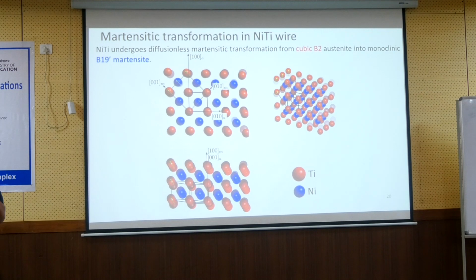when stress-induced, so far I have been saying that austenite transforms to twinned martensite. But is it true? Chluba says if you add copper, you can do it without that. We have an idea, which is not yet published, but is in two figures, that you can achieve the same with a little plasticity. So in NiTinol, you also transform between austenite and a single variant of martensite, but without having completely fulfilled this compatible condition. Because